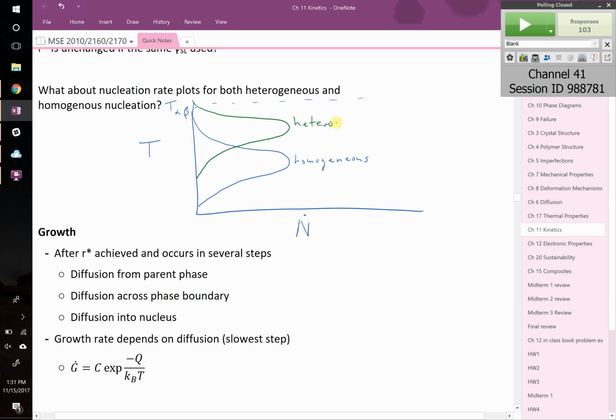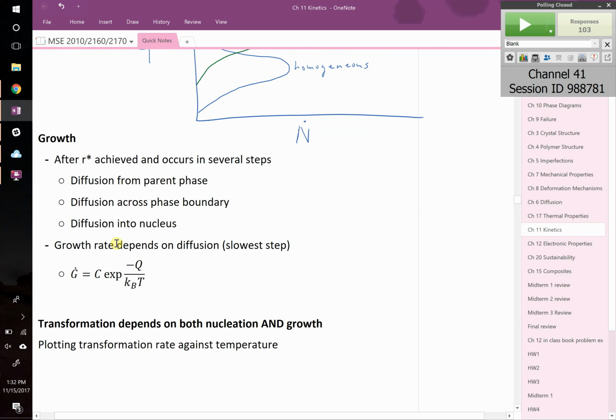Or in other words, if you have heterogeneous nucleation conditions, you won't be able to supercool it as much, right? Because there's less of an energy barrier. The energy barrier just gets cut off. So your rate is going to be faster at smaller delta T's away from your melting point. Okay? Technically we've talked about attachment rates, so the rate at which these things grow. There is a full expression for growth. It basically looks the exact same as V sub D, right? You've got some constant times your diffusion coefficient. So in the book, they actually show this separately. They show it look like this.